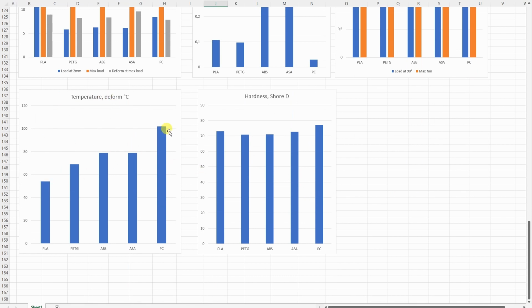And last, something I expected: the PLA was the weakest, polycarbonate was the best here. ABS, ASA very similar. I was expecting a little bit better, higher temperature here, but don't forget this is not standard testing yet. I try to make this closer to the ISO 75 standard, but that's a question for future videos. And the latest is the hardness, very similar, but of course again the polycarbonate was the hardest here. If this were a metal, then I would say that it is the most wear resistant, but I'm not sure that is the case with plastic too.